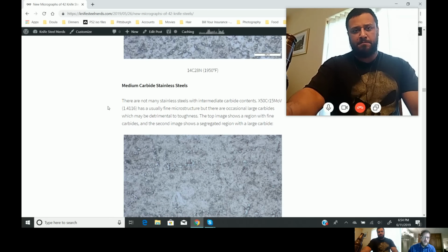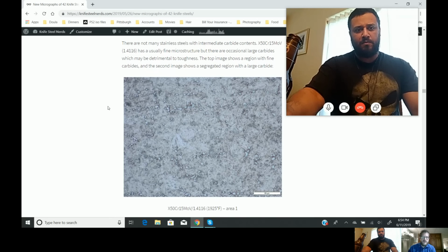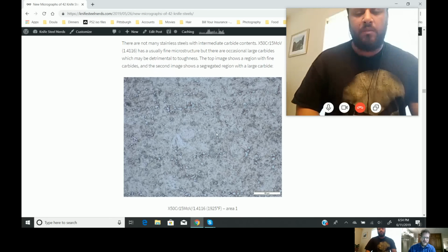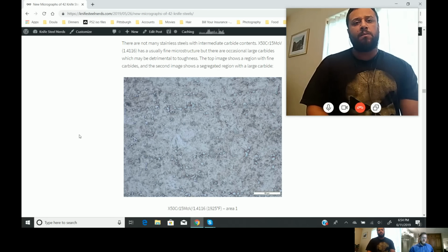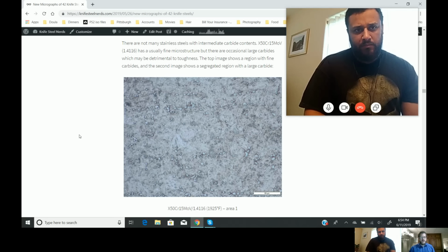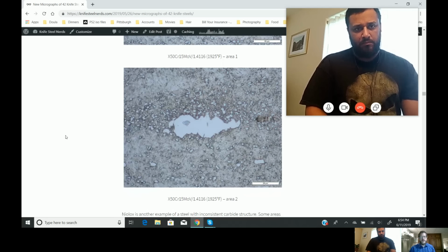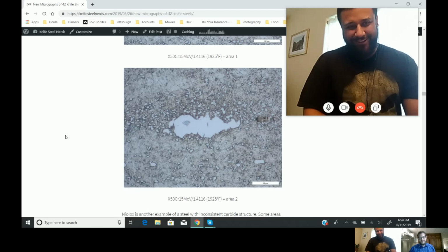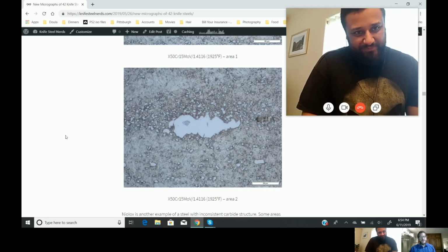Then I have some medium carbide stainless steels. These are non-powder metallurgy. So with these steels, it looks fine in some areas, but there's other areas where the carbides were not successfully broken up during forging and high temperature operations. And so there's really huge carbides left over. Oh! And those are detrimental to toughness.